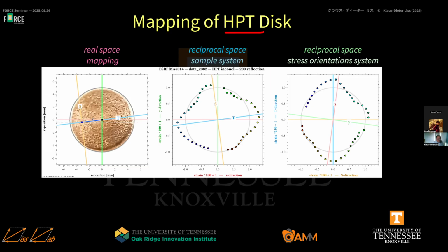And obviously perpendicular to it in the radial direction is the transverse to shear direction. Now as we go, all these spots here, position to position to position, and make a line scan. So what I have here on the right-hand side, let's take the blue spot and we look in reciprocal space. So this is the strain now. We see this is the t direction.